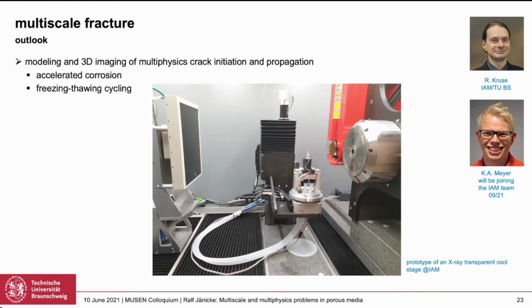So Roland Kruse started to build a prototype, and that's how it looks at the moment in our microCT. Where you see here, that's the rotating stage. And here it's not easy to see, there's a Peltier element, so we can cool down and heat up the sample. The sample would be placed on top of this piece here and put into an insulating tube. So this is something we can then manipulate in the microCT in situ. And here the pipes, we need them for the cooling of the Peltier element.